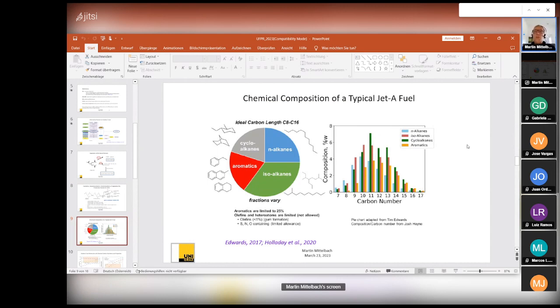Looking at the chemical composition of a typical jet fuel, it's not this sustainable one, it's just a common fuel. You see, it's a mixture of a lot of different products. It could be alkanes, but not so high chain lengths, isoalkanes, aromatics, and cycloalkanes. The carbon number you see here is between 7 and 16. It's lower boiling, of course, than diesel fuel, so it's something between gasoline and diesel, and you have to adjust the refining conditions to get such a mixture.